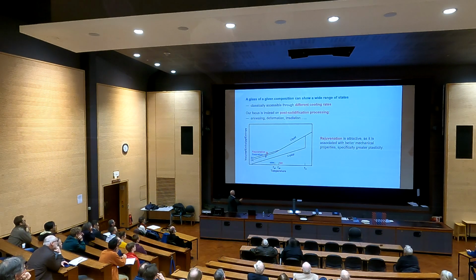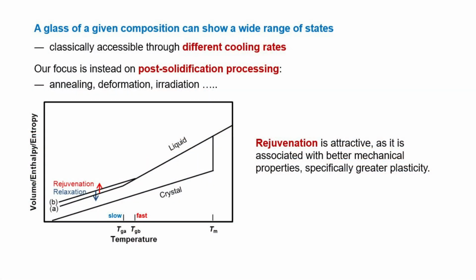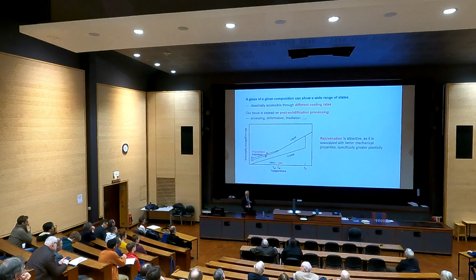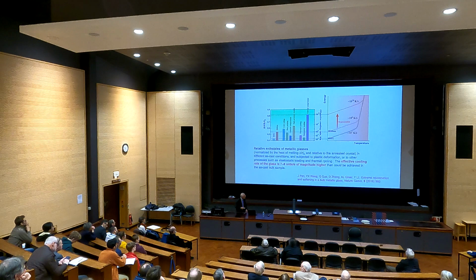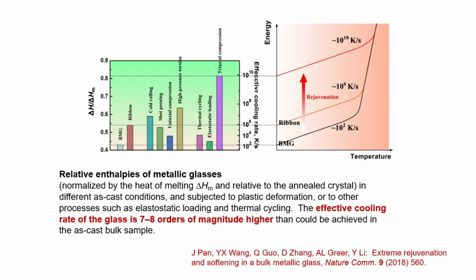Well, you can get a range of glassy structures. We know that if you anneal a glass, it goes down in energy. That's called relaxation, and that can make the metallic glass more brittle. So you actually want to go in the opposite direction. And because it's not relaxation or aging, it's called rejuvenation. You could apply lots of mechanical processes to do it and bump up the energy, which would be rejuvenation.